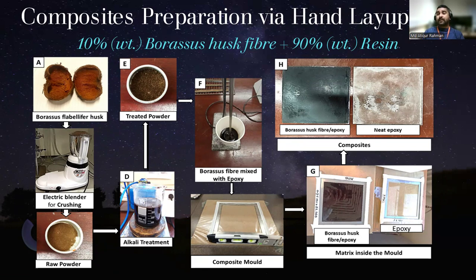I must tell you about the mixture. You can see the picture here. We did the mechanical stirring, but after that we put it into a vacuum chamber for degassing, because there might be some gas or trapped moisture. So we do the degassing process, which is not even included in the picture, so that there will be no gas, air or bubbles inside. After that we poured all the mixture into the mold. And yes, we followed the preparation method provided by the supplier. So we do the pre-curing, post-curing, and that's how the sample looks.